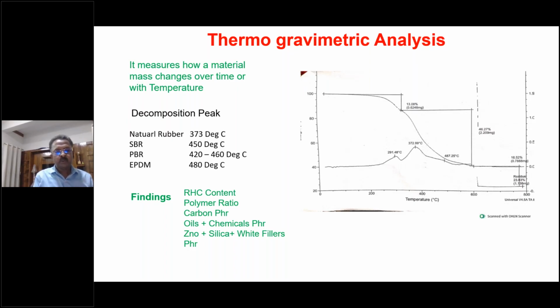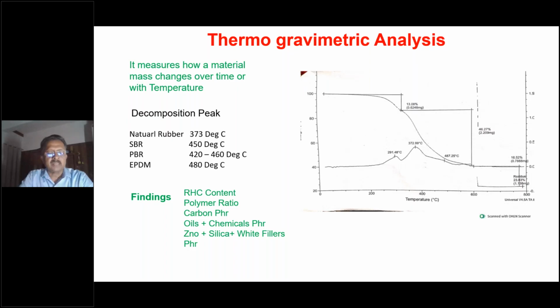So these materials decompose at varying temperatures. So in TGA, we are measuring the mass change over time and temperature. From this analysis, we can come to know the rubber hydrocarbon content. See the first part, the 13% is basically the volatiles. Volatiles are basically our antioxidants, accelerators, stearic acid, sulfur, oils, etc. Then comes the polymer.